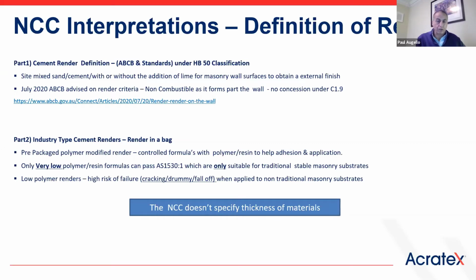from adhesion to what you're going to apply it over the top, which is no difference really to what they did on site. They used to put plasticizers in it to bring that together. Now what we do is we've got these polymer and resins that basically bring all that together. So any cementitious or polymer render that you see in the marketplace, 90% of them are all formulated very, very similar, but it's a polymer resin content that is a critical part to the system.